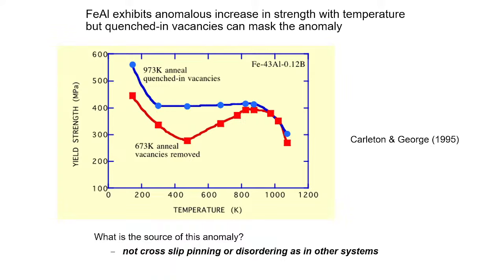But the reason is these alloys have a lot of quenched-in vacancies. Now you might think, well, why didn't people think about getting rid of the quenched-in vacancies? It turns out it's not so easy in FeAl. Unlike most materials, where the migration enthalpy of vacancies is low but the formation enthalpy is high, which means it's very difficult to form vacancies but very easy to move them, in FeAl it's exactly the opposite. It's very easy to form vacancies but very hard to get rid of them. So you have to anneal it for weeks on end at very low temperature to get rid of the vacancies that are frozen in from high temperatures.